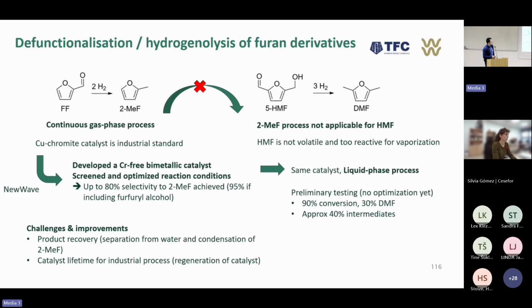So just as a proof of concept, what we did is use the same catalyst used for methylfuran production, a catalyst able to do this reaction, but then basically use the liquid phase process that we developed for HMF and combine them. Without any optimization, we were able to achieve 90% conversion and get 30% DMF production. So yes, in a sense this reaction can be done, but we still had approximately 40% intermediates and 10% residual HMF. So it's by far not fully optimized—likely for this process you will need an entirely different process than methylfuran production.